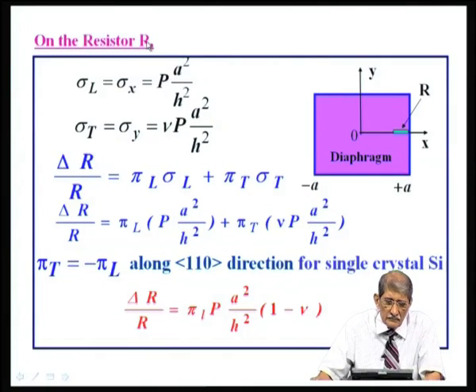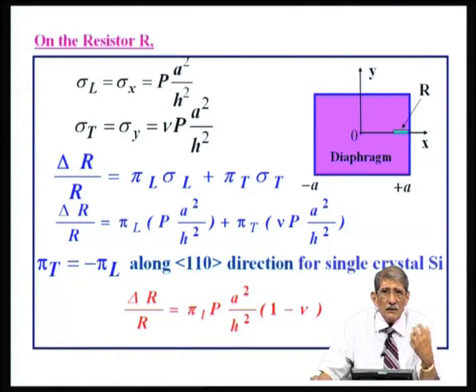Okay. Now, let us put this in terms of the piezoresistive coefficient, because for the material you will know how much the piezoresistive coefficient is, or the gauge factor. So, we have sigma L is P into A by H whole square, and sigma T is nu times P into A by H whole square. The total change in the resistance is due to the combined effect of these two. Notice delta R by R is the sum of the effects of longitudinal stress and transverse stress: pi L into sigma L, the longitudinal piezoresistive coefficient multiplied by longitudinal stress, plus the transverse value.